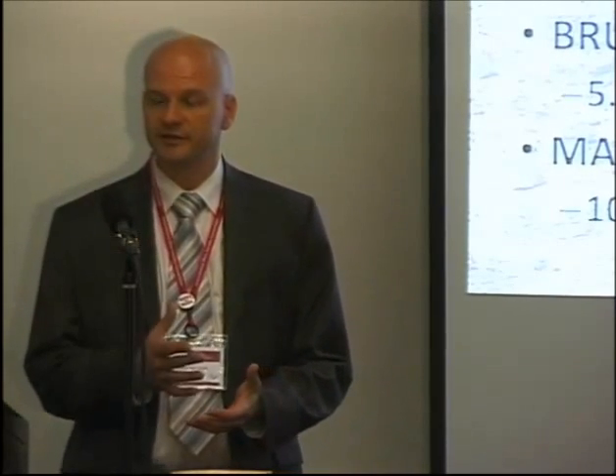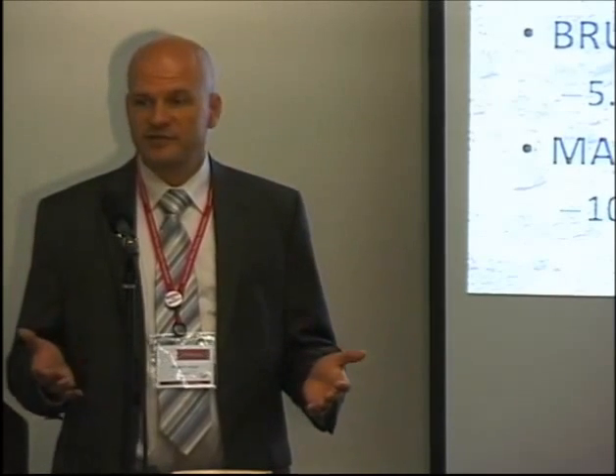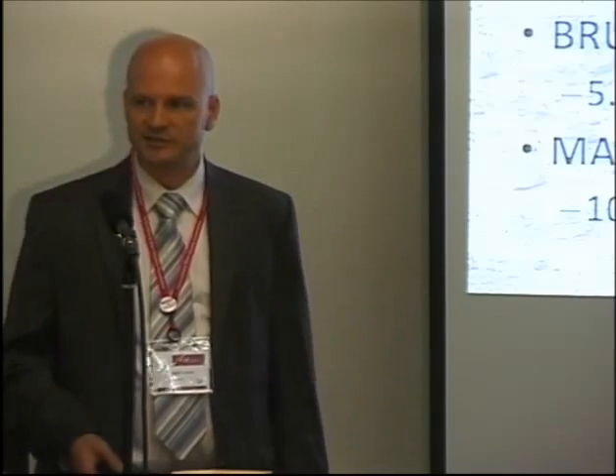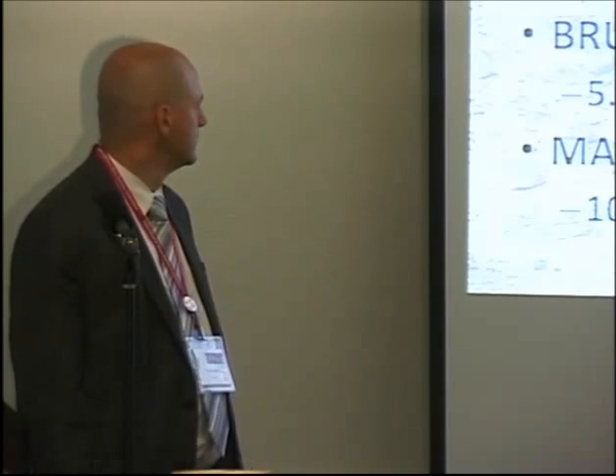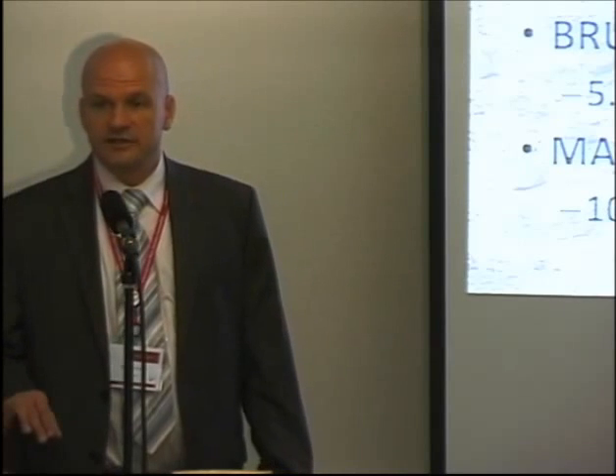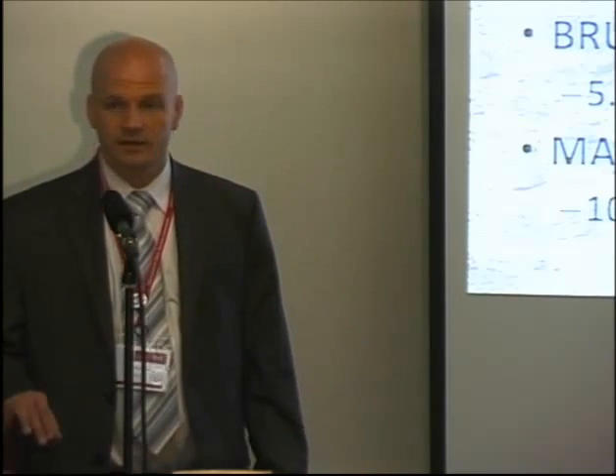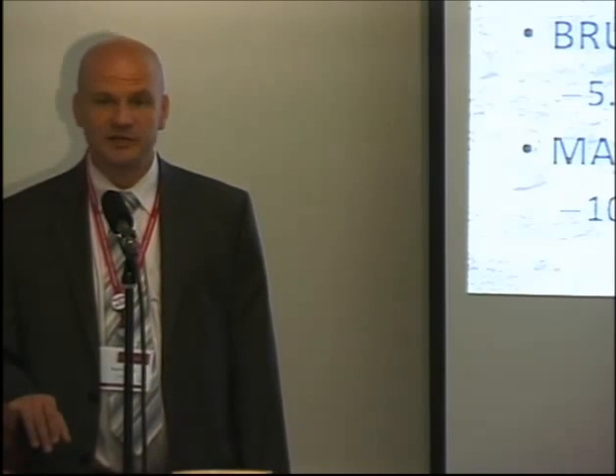Where I got those numbers was the energy required to heat the material and then the energy required for thermal decomposition, assuming 50% thermal efficiency. So I took that figure and just doubled it, just as a rough estimate. Now, if we wanted to produce it from magnesium sulfate by direct thermal decomposition, it would take over 10 million watt hours per ton, more than double that of magnesite. And a byproduct of that is sulfur dioxide and sulfur trioxide, which would present problems with exposure to the equipment, since that, when combined with water, produces sulfuric acid.